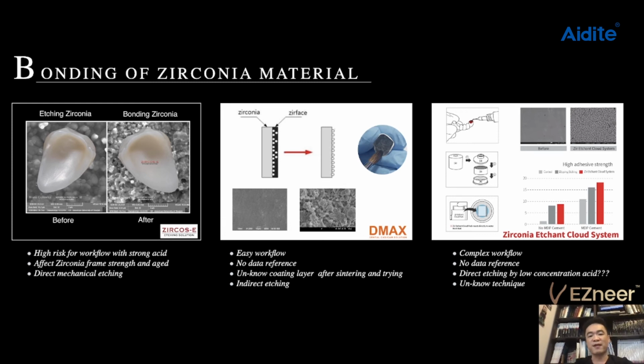And maybe DMAX, they have applied a special glass liquid, which you can apply before the sintering. But after the sintering, we don't know the release or how much glass is on the surface. And after the try-in, maybe they will be damaged or we will lose it. And the bigger problem is we can't find any data about this solution. So it's like a secret, and we don't know the bonding strength for this technique.